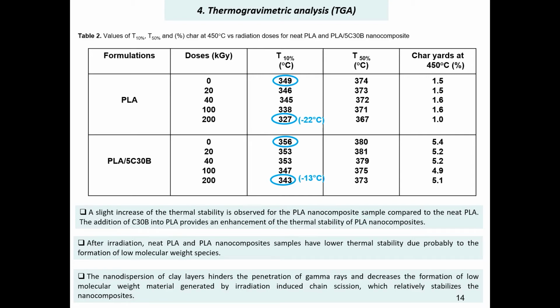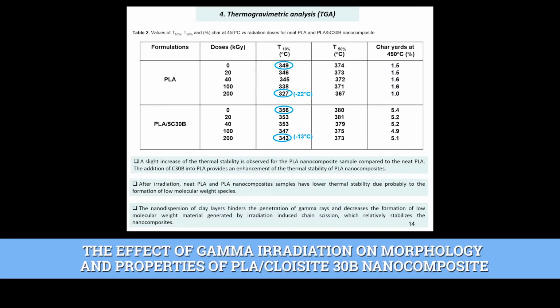After exposure to gamma irradiation, it is clearly shown that both neat PLA and PLA nanocomposite samples have lower thermal stability with increasing the radiation dose, due probably to the formation of low molecular weight species. However, due to the nano-dispersion of clay layers, this hinders the penetration of gamma rays and decreases the formation of low molecular weight materials generated by irradiation, and subsequently this can be considered as a stabilizing system by the presence of the C30B.